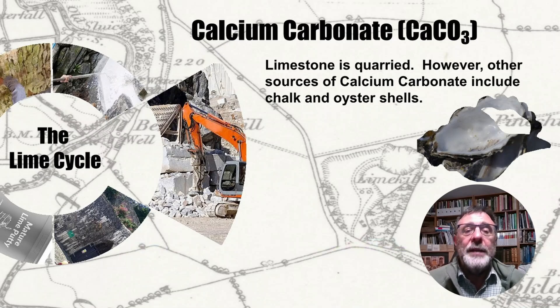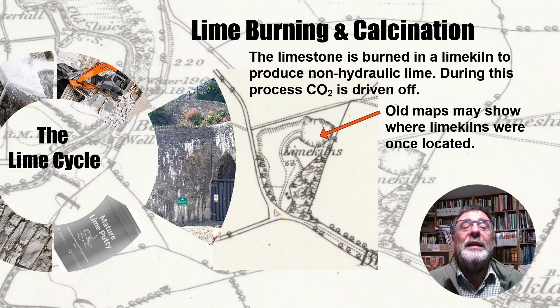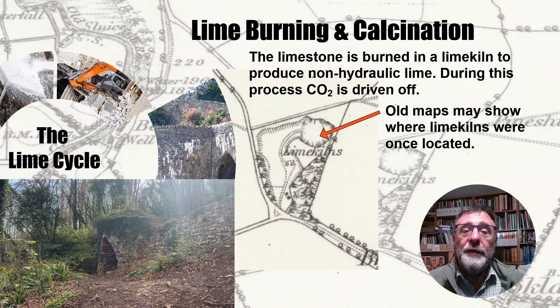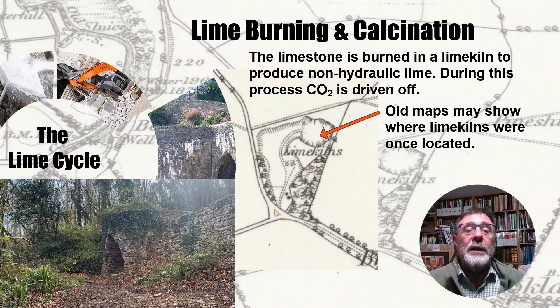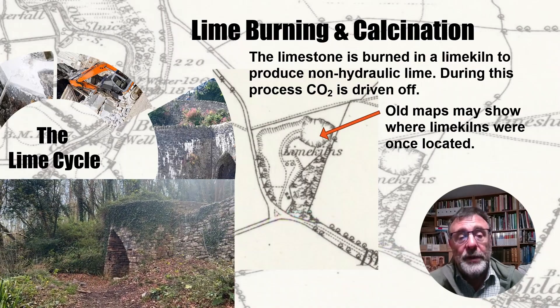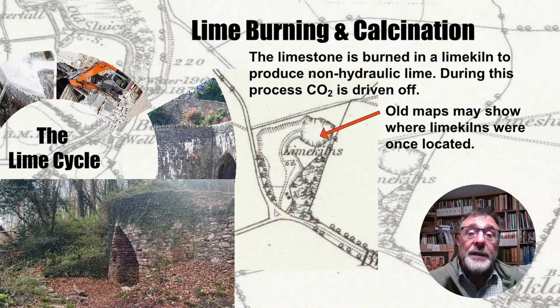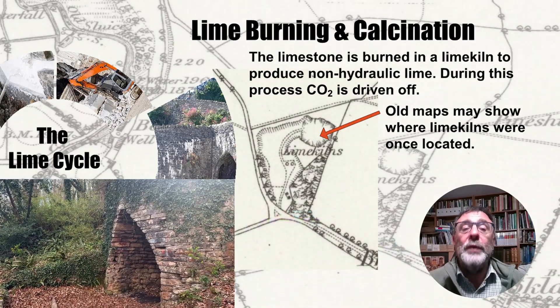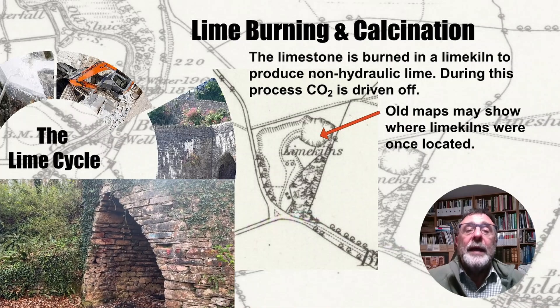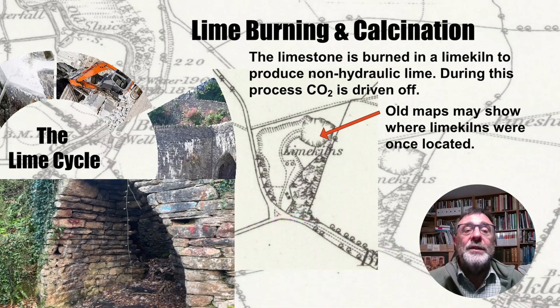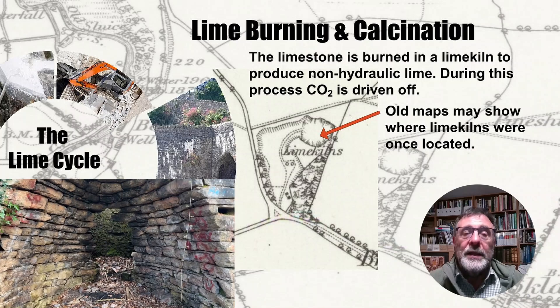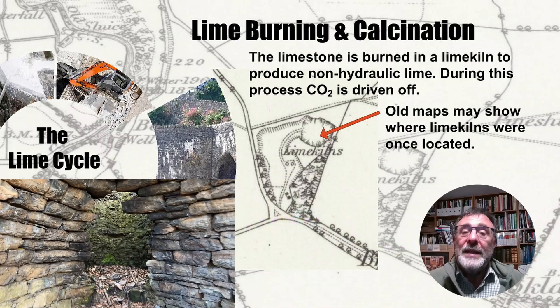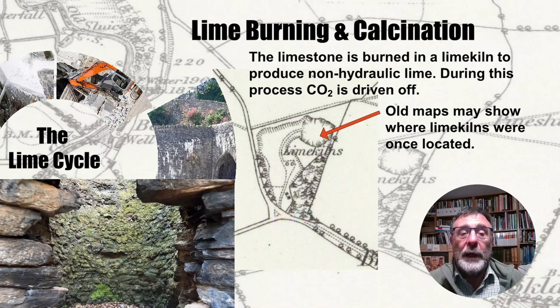The calcium carbonate is taken to a lime kiln where it is burned. The temperature of the kiln has to be at least 840 degrees centigrade and it is most efficient when operating between 900 and 1000 degrees centigrade. At these temperatures, the calcium carbonate undergoes a process called calcination, where it releases carbon dioxide and forms calcium oxide — what we commonly refer to as quicklime.